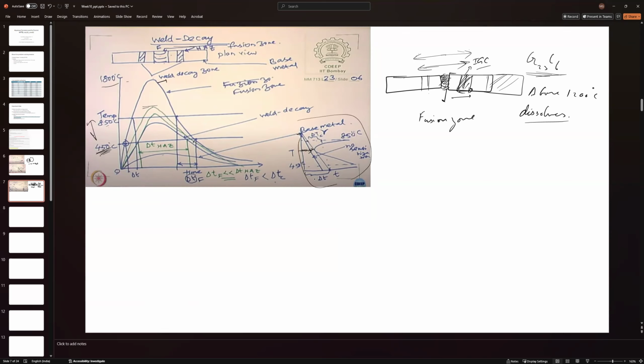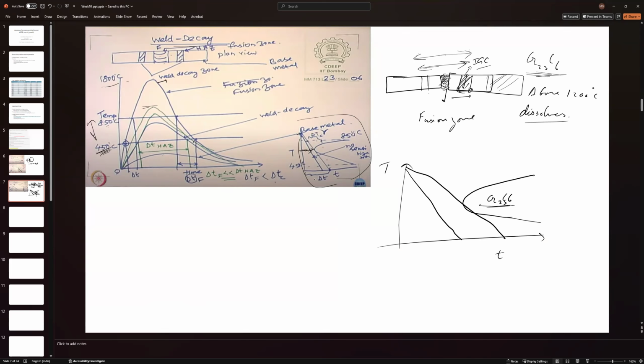Let's understand this plot. This was your TTT plot, time temperature transformation. Suppose you start from here and you cool it very fast, you don't enter this region where chromium carbide precipitation is forming. So no sensitization happens. So this is your chromium carbide formation region. However, if your cooling rate is low enough, you cross this region and you form chromium carbide precipitates that will lead to IGC, sensitization of the sample. So what matters here is the time. You're starting from the same temperature, but you're cooling at different times, right? How much time you spend in this region is important.